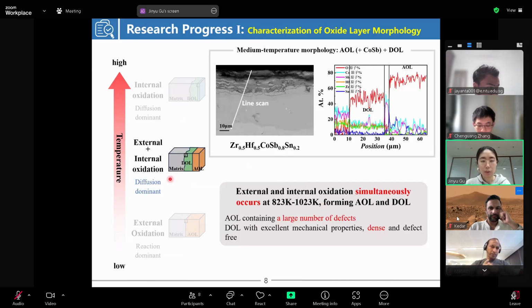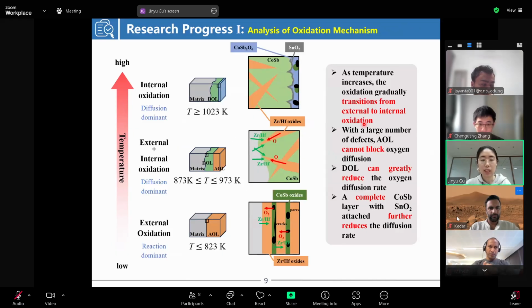In the mid-temperature range, mass gain also follows the parabolic relationship. The material undergoes both external and internal oxidation, and the typical oxide layer morphologies, namely AOL and DOL, also appear simultaneously. It can be concluded that as the temperature increases, the oxidation gradually transitions from external to internal oxidation. And AOL cannot block oxygen diffusion, while DOL can.